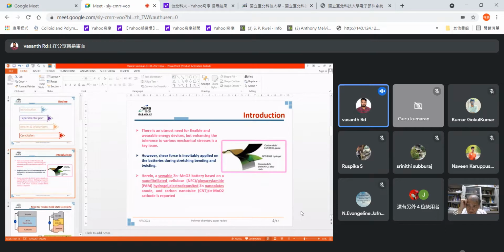The introduction is about the utmost need for flexible and wearable energy devices, but enhancing the tolerance to various mechanical stress is the key issue. However, shear force is inevitably applied on the batteries during stretching, bending, and twisting. Herein, a sewable zinc MnO2 battery based on a nano fibrillated cellulose with polyacrylamide hydrogel electrolyte, with zinc nanoplates as anode and carbon nanotube MnO2 as cathode, is reported. As you can see from the image, carbon cloth is used as a substrate in the cathode, and NFC PAM hydrogel is used as a flexible solid electrolyte, deposited over the cathode and the anode material, which is zinc nanosheet.